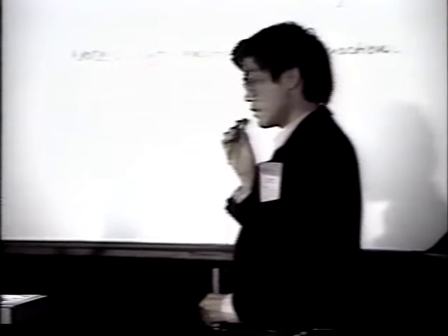My second assumption is that there's a strong phonon-mediated interband scattering. This phonon in the lanthanum-bearing compound, we believe, is associated with the rocking of the oxygen octahedron, or can be associated with the Jahn-Teller distortion. Such an interband scattering process introduces a term like this in the Hamiltonian. We know that such a term is not a density-density interaction. It's a purely off-diagonal scattering term.